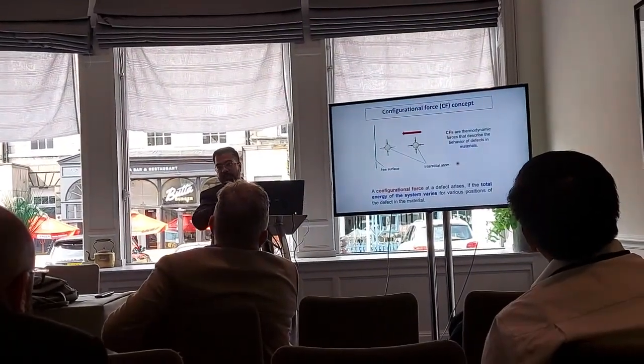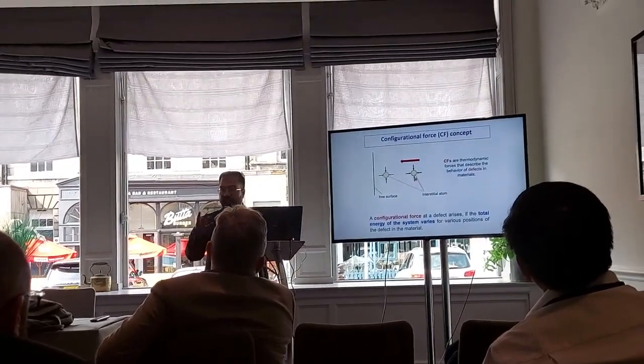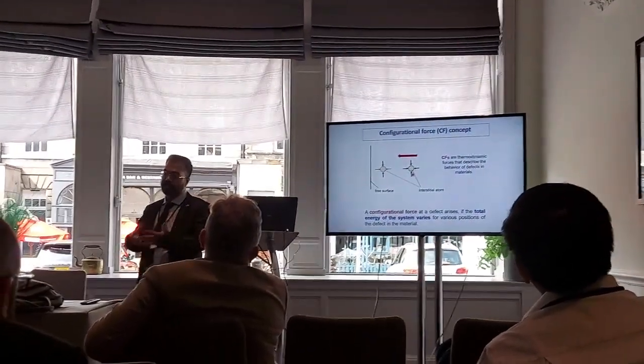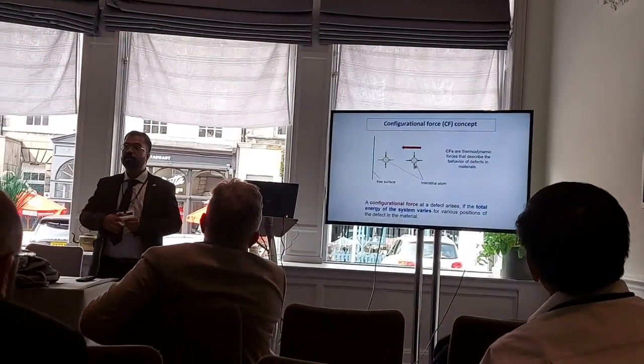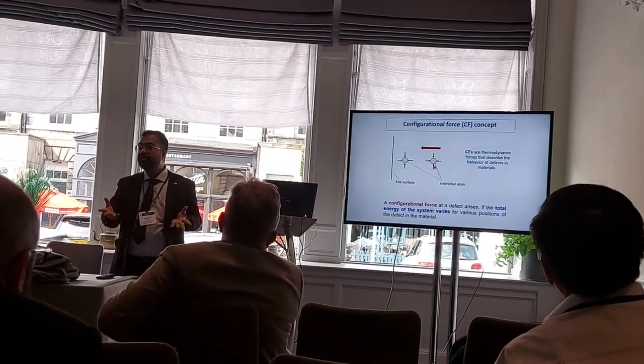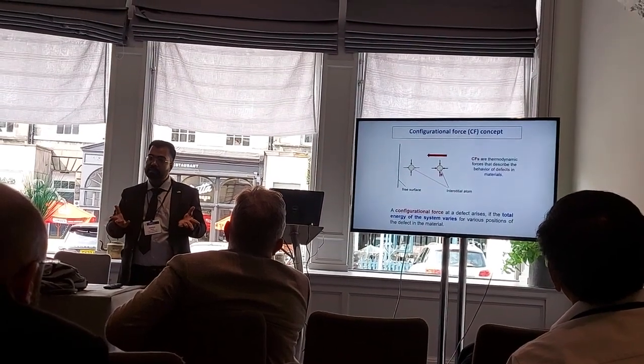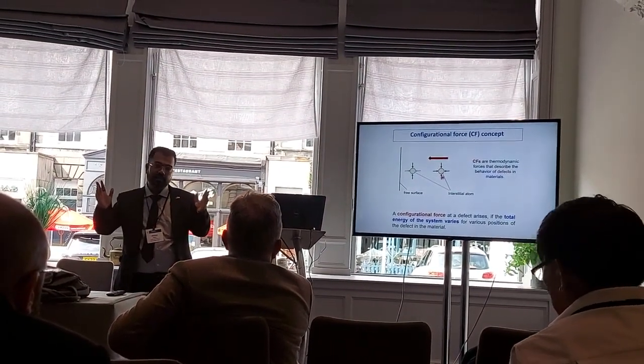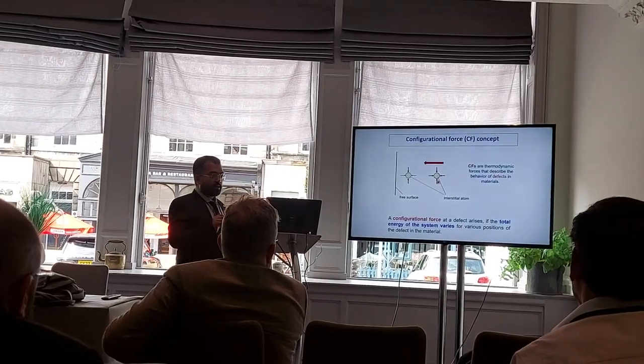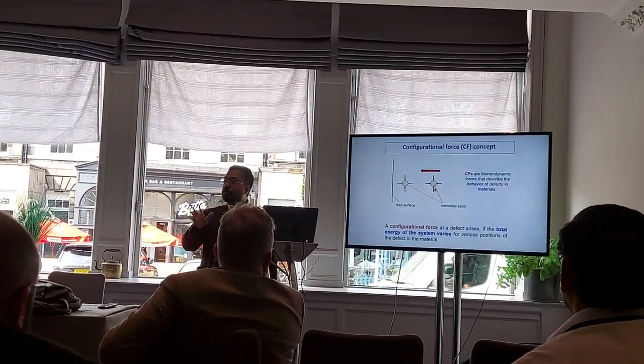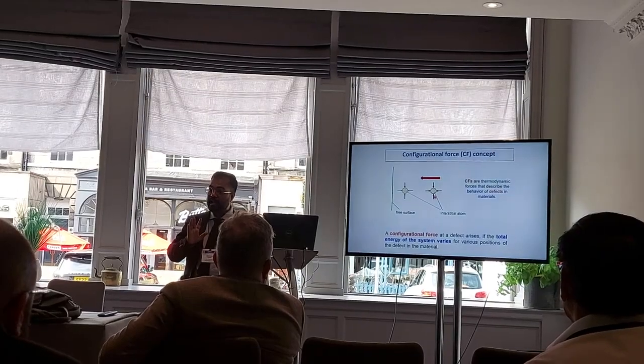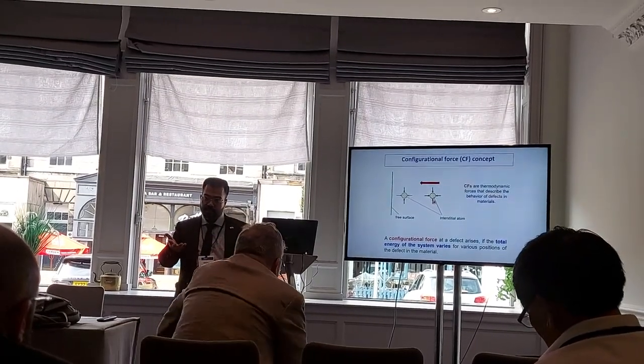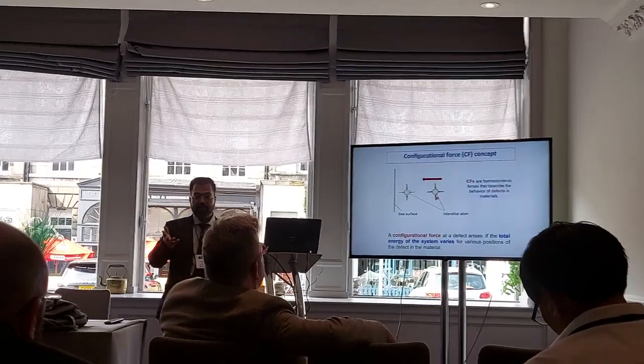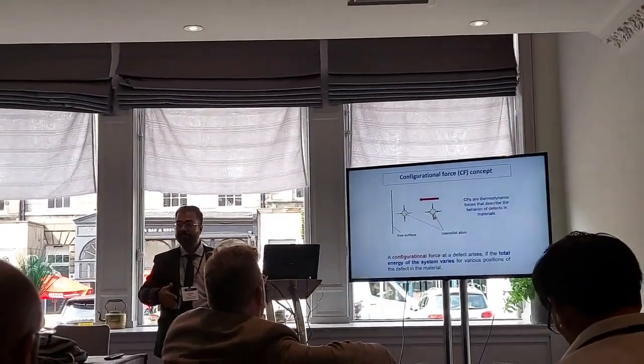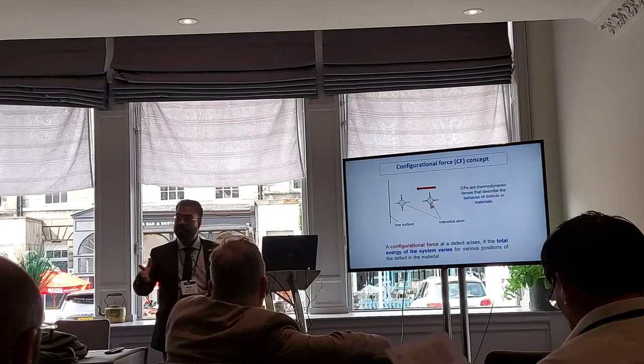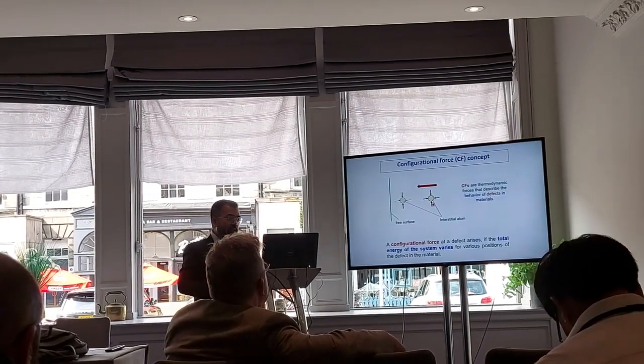In this example, you imagine an interstitial atom which is sitting inside the material, so that is compressed by the bigger atoms surrounding it, so it is not happy. If it goes to the surface, then at least half of them are gone, so a little happier situation exists. So there is an energy gradient, and because of that there will be a force which will compel this interstitial to go to the surface. Whether or not this will happen depends on the path available. So the force is there, but the interstitial may not go to the surface because the microstructure will stop it, because you have an energy barrier in going there.